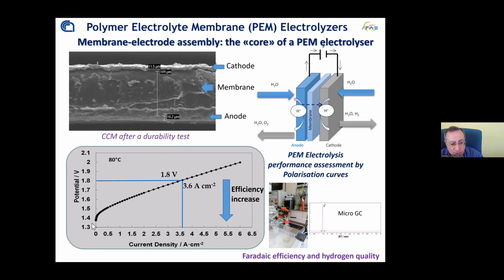Of course, we cannot decrease the operating voltage below about 1.4 to 1.48 volts at ambient temperature, because this is the thermoneutral potential. This is limited by thermodynamics, so we cannot achieve something not permitted by thermodynamics. The thermodynamic limitation is about 1.4 volts, but we can decrease the cell voltage to approach this value.